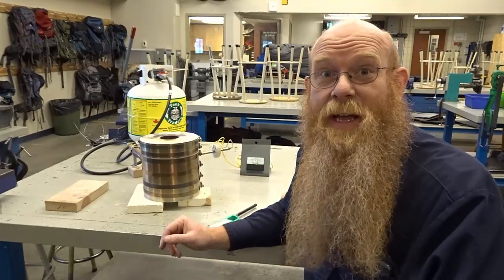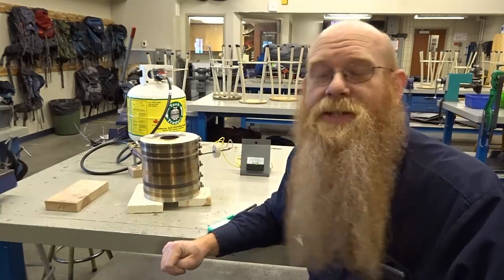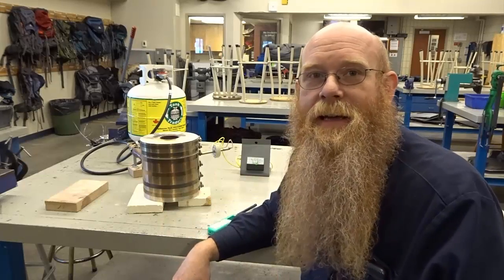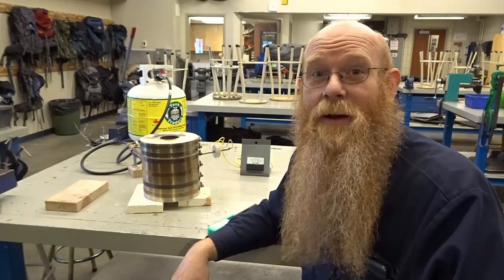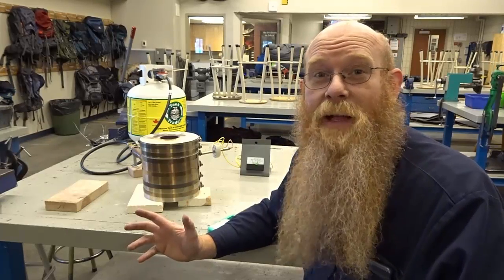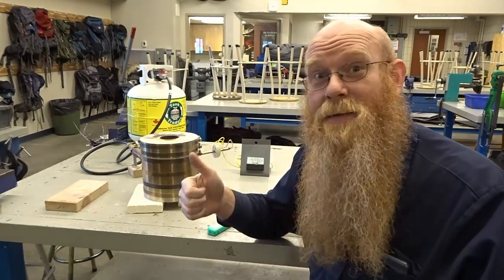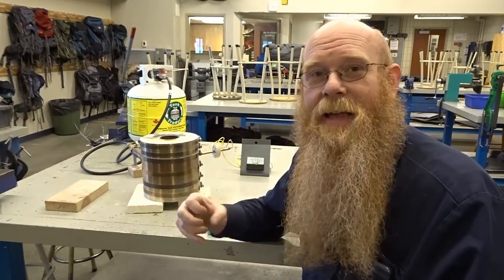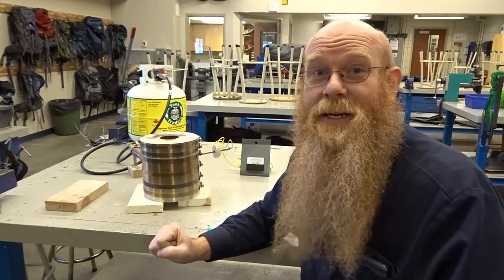The gold I got yesterday on the Miller table, just over two grams, has a bit of black sand in it. So I will be using a flux that can easily take up that black sand, get it out of the gold, and leave me a fairly clean gold bar. When I do these smelts I'm not getting 100% pure gold into the bar because there are still some metals like silver and copper that don't go into the flux and stay in the gold.